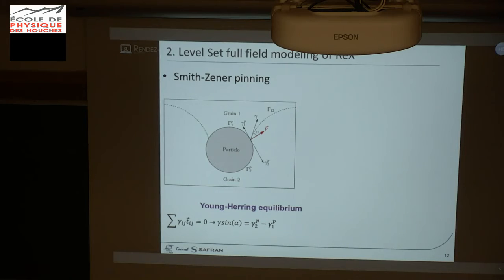If you use the same Young-Herring equilibrium, which is finally the link between the angle of interaction between the grain interface and the particle interface energy and the grain interface energy, you can obtain the equation at the bottom left side of my slide, which is a relationship between the angle alpha between the grain interface and static particles, and the difference of energy of the system.